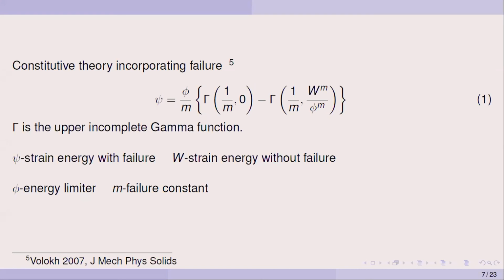Okay. So is there any broad similarity between this approach and the more popular one, which is the phase field models for damage or fracture? Is there some similarity in terms of introducing additional parameters to incorporate damage? Because I'm wondering, where does localization come, right? In phase field models, often you see some explicit length scale, and that kind of tells you that there could be localization. In this case, I'm unable to see a length scale, at least without understanding what is phi and m.